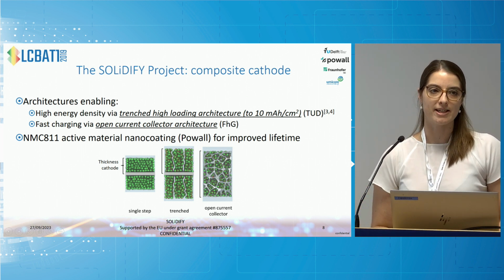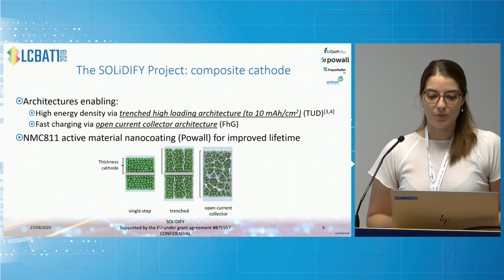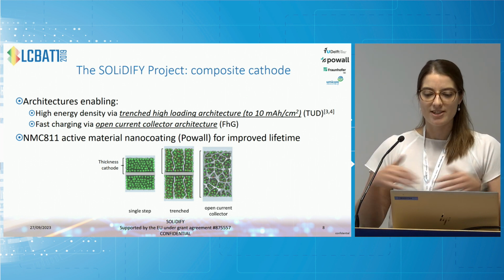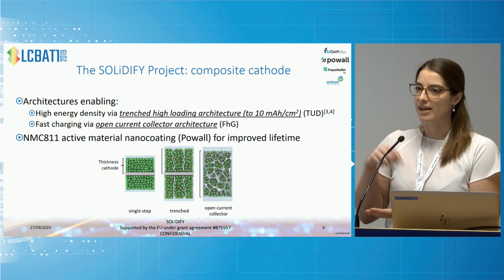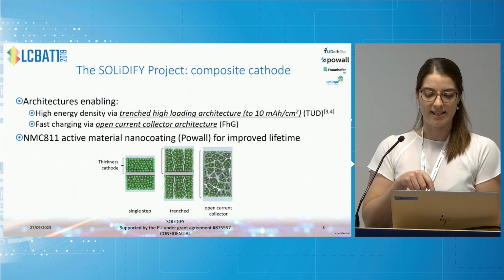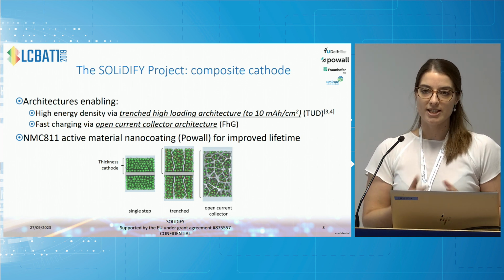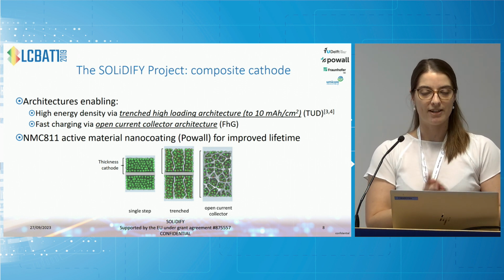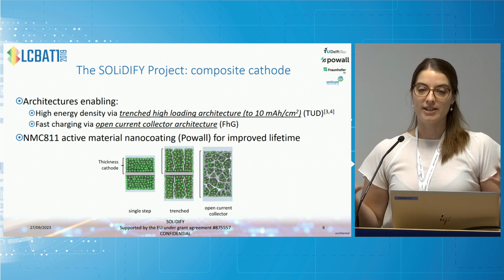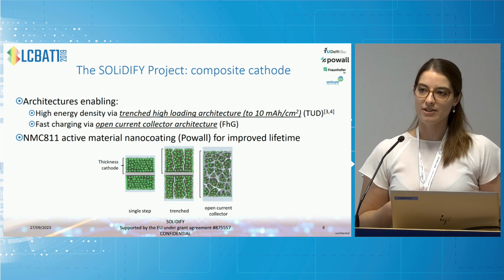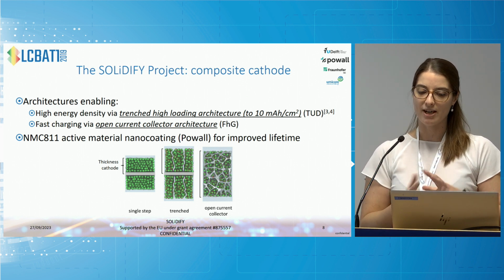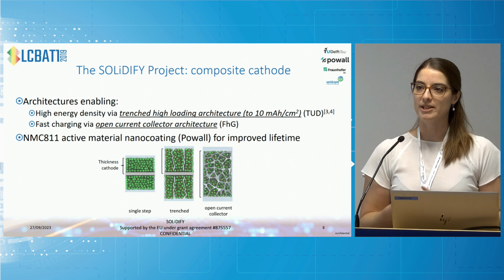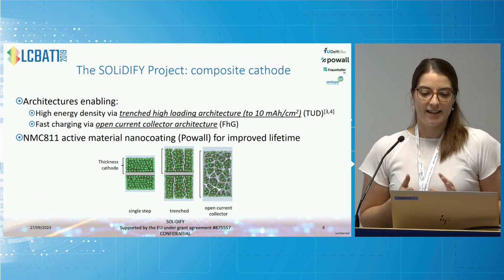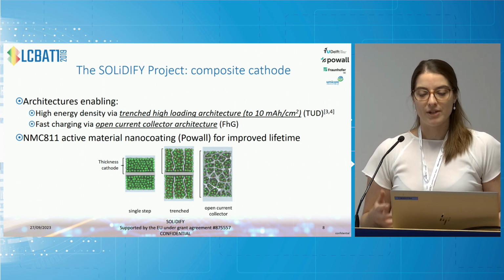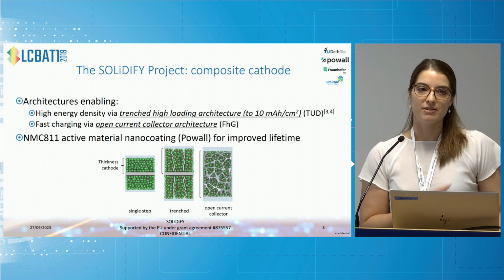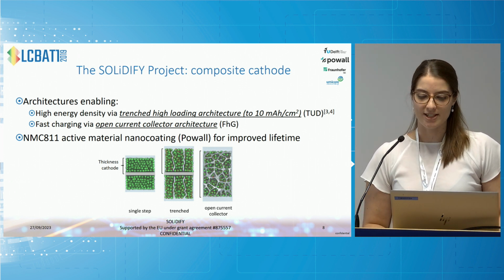I've got the references here if you're interested as well, where effectively, say trenched, perhaps a little misleading, we have like pinholes in the cathode itself. And this actually enables, one, for the cathode to be quite flexible. One of the aspects is that we want to use high-loading cathodes, and this pinhole architecture really helps with the flexibility, formability of the cathode. And then secondly, it really also helps improve the infiltration of the electrolyte into the cathode itself.